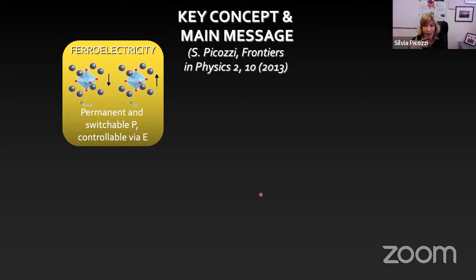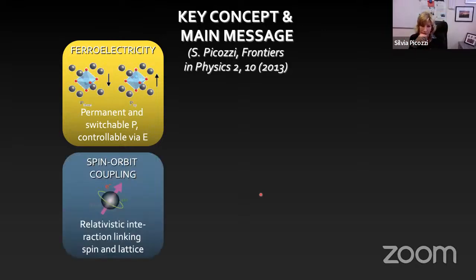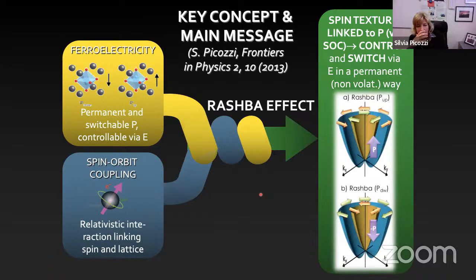And so it's not only that I have this long range order, the other requirement a ferroelectric needs to satisfy is the switchability. So I need to be able to switch by applying an electric field from a positive polarization state to a negative polarization state. And so if I have a ferroelectric material and I have spin-orbit coupling, significant spin-orbit interaction, then by means of the Rashba effect, I can basically get a peculiar effect.